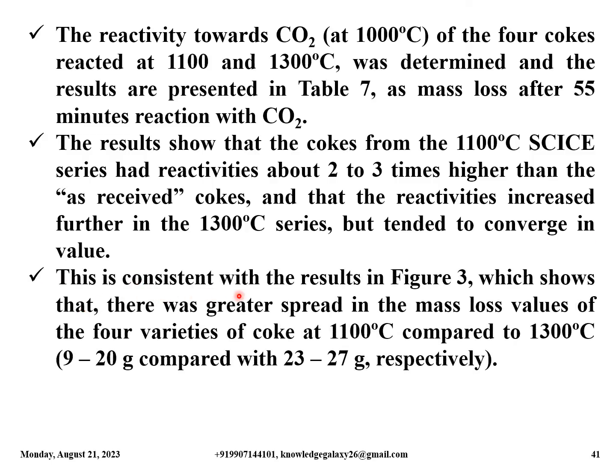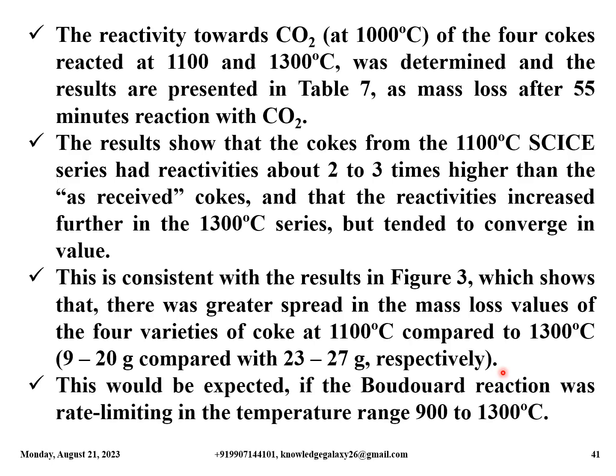This is consistent with the results in figure 3, which shows that there was greater spread in the mass loss values of the 4 varieties of coke at 1100 degrees Celsius compared to 1300 degrees Celsius, that is 9 to 20 gram compared with 23 to 27 gram respectively. This would be expected if the Boudouard reaction was rate limiting in the temperature range 900 to 1300 degrees Celsius.